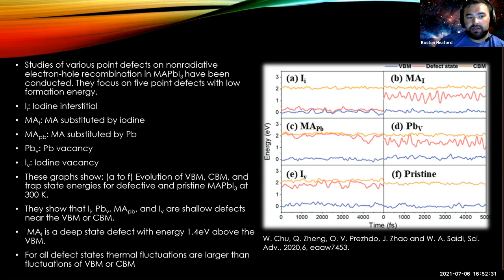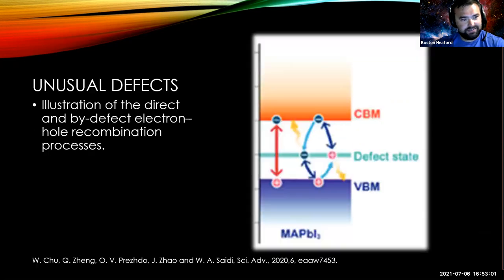And for all these states, the thermal fluctuations in the defects are much larger than the fluctuations in the valence band maximum and conduction band minimum. And so these states are where electrons or holes can get trapped in and then recombine, which again lowers their lifetime. So typically you want to avoid those, although sometimes they can be useful, as we'll soon see.